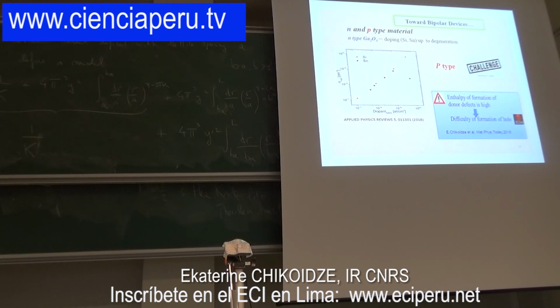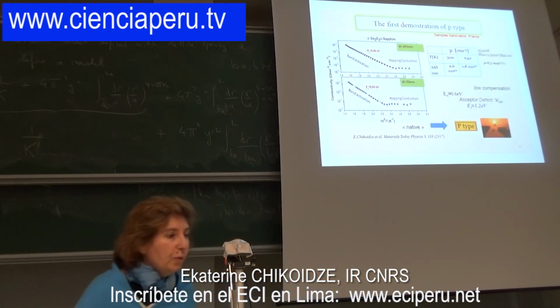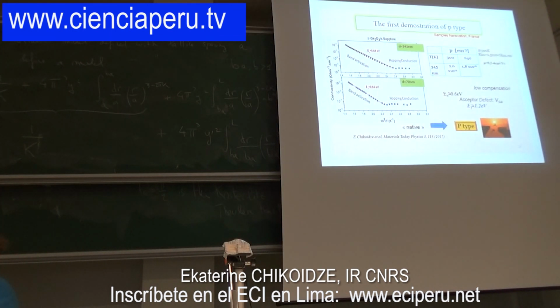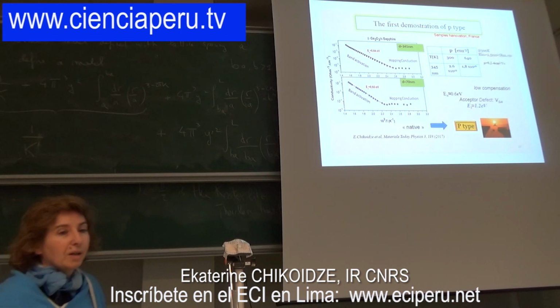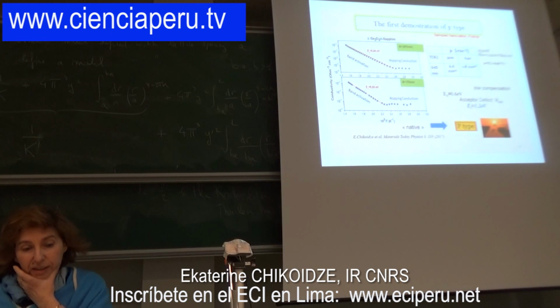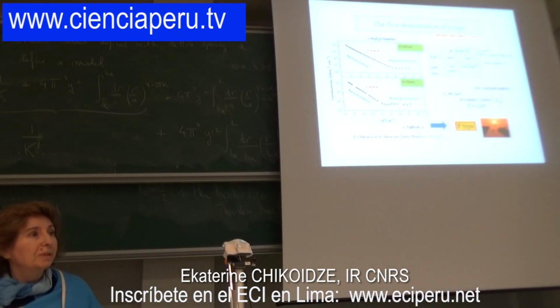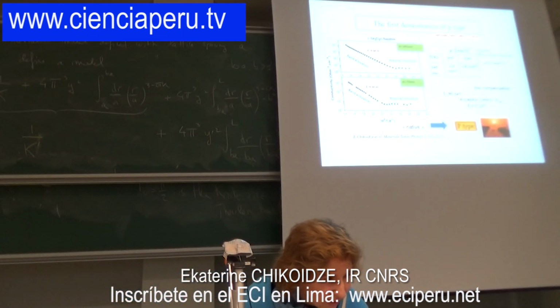thermodynamic estimation was a very good message for us to put effort into experiment, and in fact the growth was done at Nanovation, a small SME company in France, very close to Versailles. After measuring in GEMaC, we found that indeed the gallium oxide was p-type, and we were of course very happy because it was the first demonstration by us that it's possible to realize p-type conductivity in gallium oxide. Before this, the whole community was very skeptical, saying that p-type conductivity in gallium oxide is not possible because of the very wide band gap, but fortunately it was done.